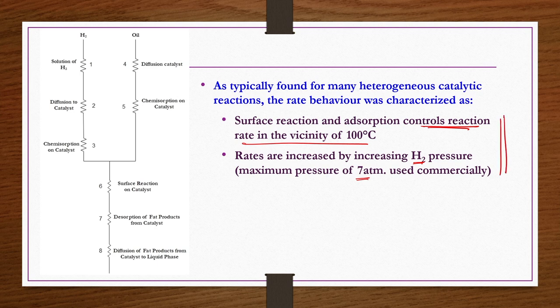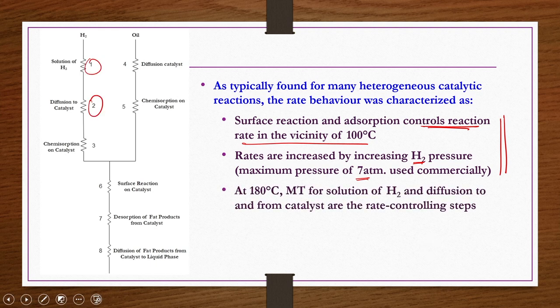So these are the observations from realistic conditions, right? So one has to do the experiments and then find out these conditions, okay? They are not obtained by mathematical or theoretical calculations. At 180 degree centigrade, mass transfer for solution of H2 and diffusion to and from the catalyst are the rate controlling steps because of higher energy requirement for these steps. So that is all about the hydrogenation of oils.